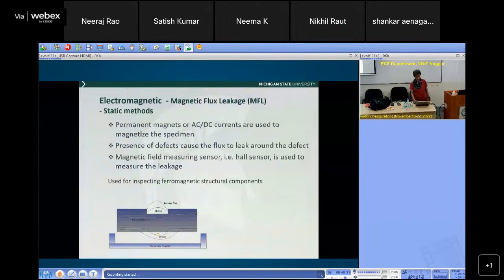So far I looked at all the other types of sensors. This I'm going to go over rather quickly because we will be talking in large detail tomorrow and in the next couple of days. Electromagnetic sensors cover the entire frequency spectrum from zero frequency to terahertz, okay? Some of the very, very low frequency methods are the magnetic flux leakage. These methods use permanent magnets or current magnetization, and so it sets up a magnetic field. When there is a defect, some of the flux leaks into the air, and then you pick that up with some kind of a field detector. And then you produce a signal corresponding to the defect. Again, the only thing is it's used for inspecting ferromagnetic structures. As I said, this won't work with aluminum, right?